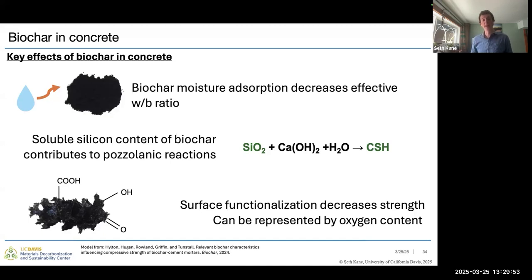In addition, the silicon content in the biochar will contribute to pozzolanic reactions. This is very similar to some of our other common supplementary cementitious materials that are high in silica and promote the formation of calcium silicate hydrate rather than calcium hydroxide, which we know increases the strength in our concrete as a result of that silicon in our biochar. And then finally, different surface functionalizations in the biochar can increase the hydrophobicity of that biochar, which might decrease the interfacial strength between it and our cementitious matrix. This can be represented pretty well by the oxygen content of the biochar, and reducing that can improve the strength overall of our concrete with biochar.